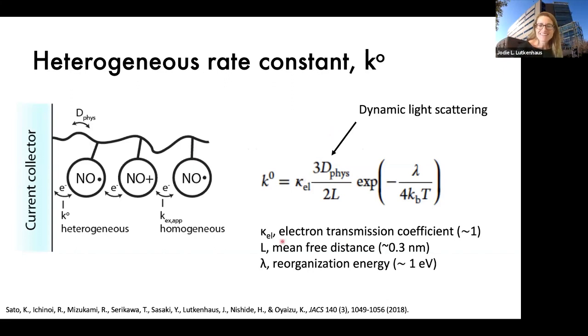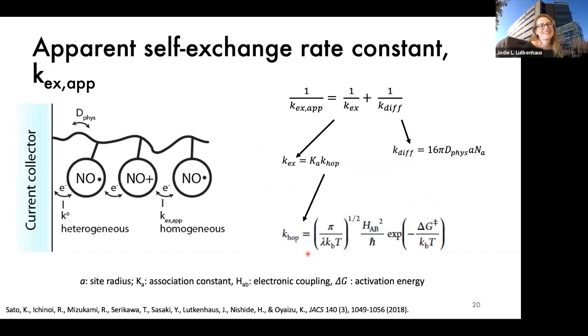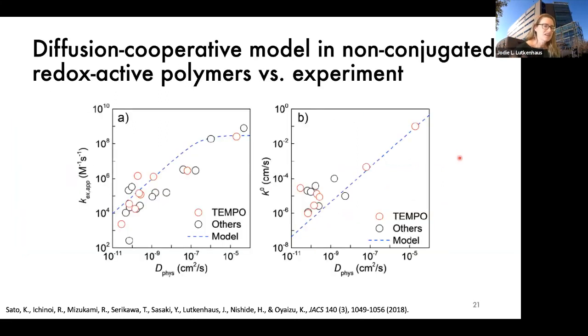So that's also dependent on the electron transmission coefficient, the mean free distance, so that hopping distance, and a reorganization energy. And the other rate constant we consider is the self-exchange rate constant. So that's from site to site. So besides considering Marcus theory, we also consider the contribution from diffusion of the polymer chain. So together, that allowed Kahn to develop this model, which is the blue dashed line, for the self-exchange and the heterogeneous rate constants, and experimentally measure those constants in our lab for that series of polymers I showed you. So the agreement is not perfect, but it's also not terrible either. And I think the agreement is much better than previous models.